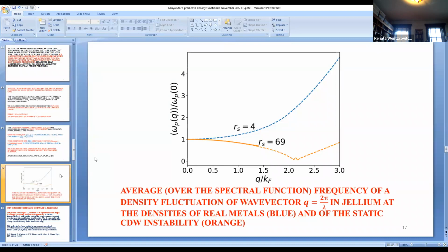In jellium at these densities, first for real metals—blue, RS equals 4—corresponds to the valence electron density of solid sodium. There you can see the plasmon disperses upward. It starts out at the bulk plasma frequency omega p0, and as you increase the wave vector, the plasmon frequency rises monotonically.